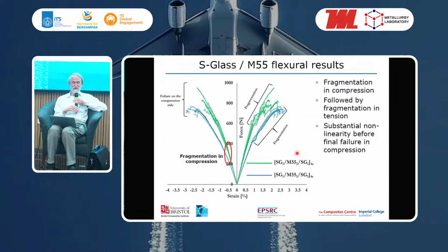And this shows the results, which I think is very interesting. Let's look first at the single ply case. This is the green one. Initially it loads up, and this is showing the strains on the compression side and the strains on the tension side as we increase the load. You see that at about 0.5% strain we get fragmentation in compression. It's not very noticeable, but there's a bit of a change in slope at this point here at about 0.5% because it's fragmenting in compression.